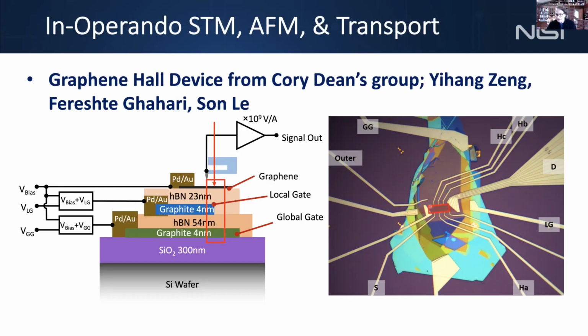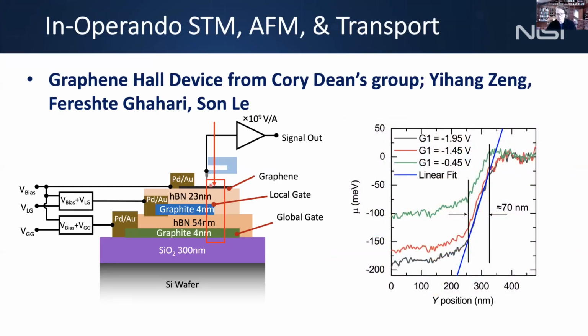So this is the region of the Hall bar. This is the interior region, and then the outside is the exterior region. When we look at the edge states, we go from this interior region to the exterior region. We can map the potential across the Hall bar, and that's shown here. You can see the potential boundary is very narrow. This is because we have the graphite backgate close to the graphene layer, so the potential is very sharp. If you tried to measure the edge states with SETs, you wouldn't be able to resolve it, because the SET typically has 100 nanometer resolution.